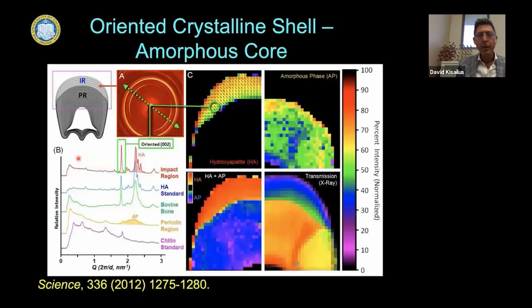stresses. So we've gone in and analyzed the club, and indeed, we found that it's made of hydroxyapatite mineral. It actually has a graded structure. That impact region that has that sinusoidal structure actually has highly oriented hydroxyapatite crystals that are more or less perpendicular to the impact surface. But inside the club, where that periodic Bouligand structure is, it's amorphous mineral.